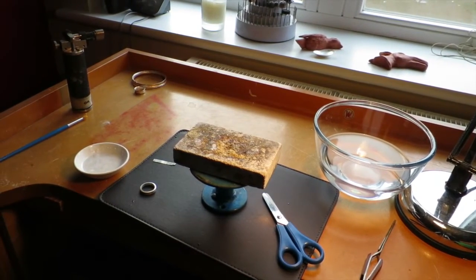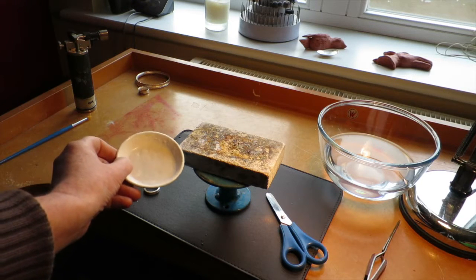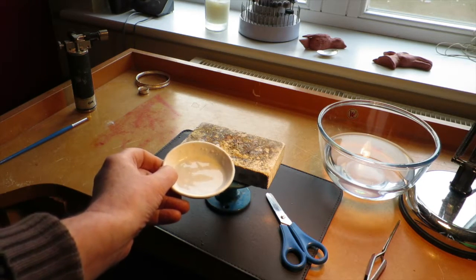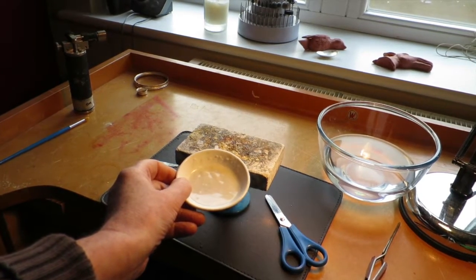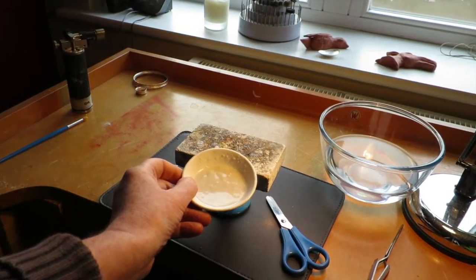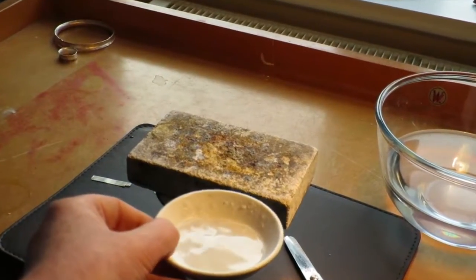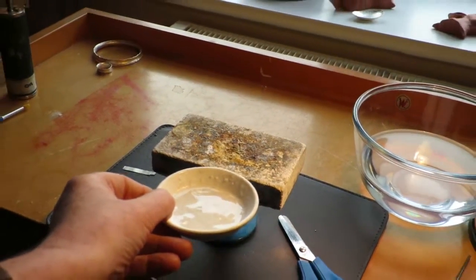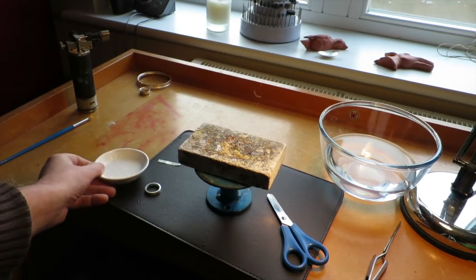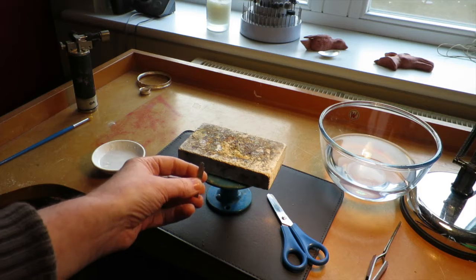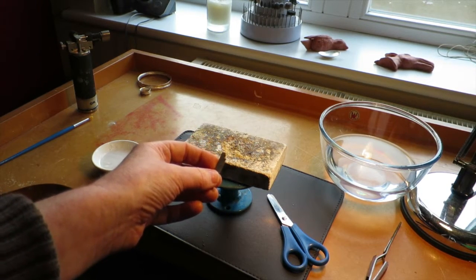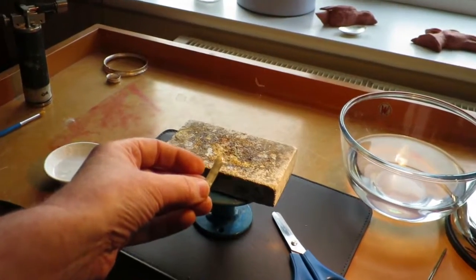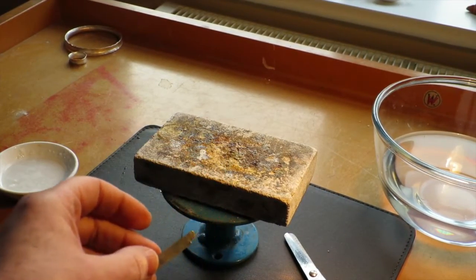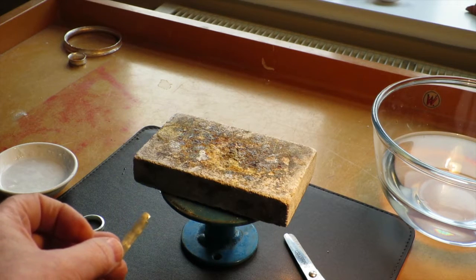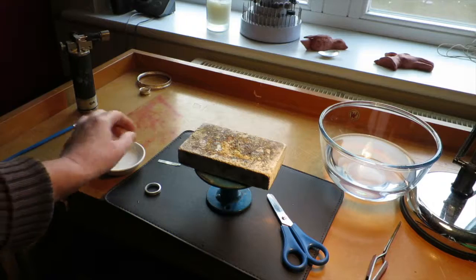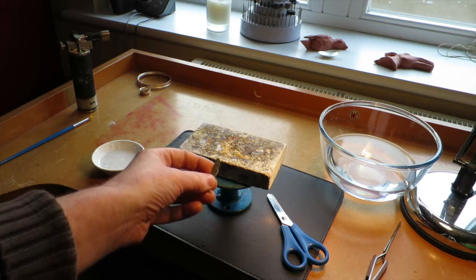So I've got water, I've got insulated tweezers, I've got flux. This is easy flow flux mixed with water. You'll be using borax cone, but single to double cream consistency is the thing to aim for. And then we're going to be using hard solder. The solder comes in thick pallions there, and we roll it down. We're using hard solder, which melts at 775 degrees centigrade. This means that we can then solder other things onto it with medium and easy solder. And we have extra easy solder, which is the lowest melting point in case we need it.